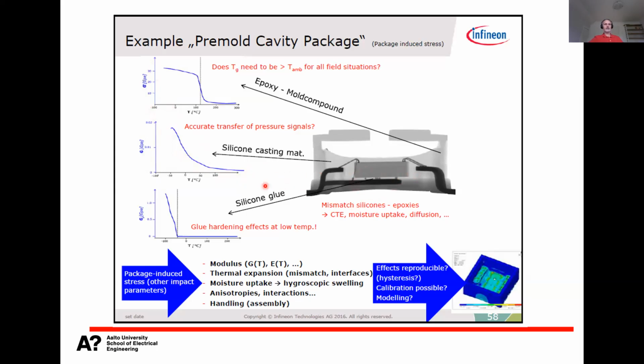And then there's the third one, which is silicone glue, more rigid, but still silicone, which is used to attach the pressure sensor to, let's say, the lead frame, the component substrate. So here also you need to have certain flexibility so that the external stresses are not transferred into the membrane. So that's the reason to use silicone glue. But the silicone glue has this kind of behavior that typically in silicones, the glass transition temperature is somewhere way below zero, typically something like -30, -40. So it is very soft in normal operating conditions, but then when the temperature drops below that critical value, this becomes very rigid. And then it is not anymore able to stop the external stresses affecting the actual component.